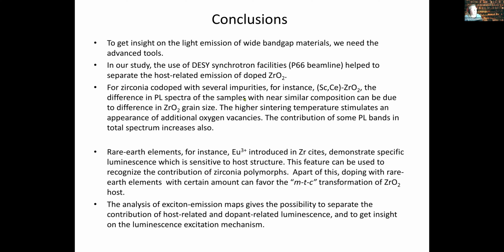For instance, europium is quite good. And if europium is situated in zirconium sites, it demonstrates specific luminescence that can be used to see the contribution of different polymorphs, or it can favor monoclinic to tetragonal phase transformation of the zirconium host. And I'm very thankful to Evgenia, who helped us to use exciton emission maps, because they really give more answers to the questions we have. And we are not running for each specific spectrum. We can use these maps to do analysis and actually to get insight into the luminescence mechanism.